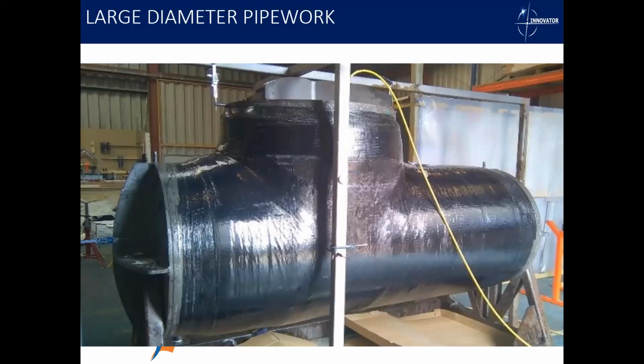So this was for a client out in Milan, and what they wanted was, I think, a 42-inch or 36-inch T-piece, and they wanted several through-wall defects machining into this T-piece. What you might also be able to see is vernier gauges set up at the top and at the side of the T-piece as well. So the intention of the test was actually to see if we could seal up the through-wall defects.